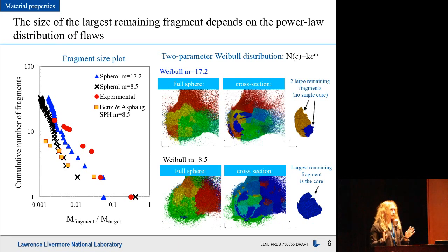However, this is not as alarming as it may seem. Simply by varying the random seeding of flaws in your target material, you would change the largest remaining target fragment mass and match the experimental findings within some error bounds. But the distribution of the smaller fragment masses is expected to stay the same.